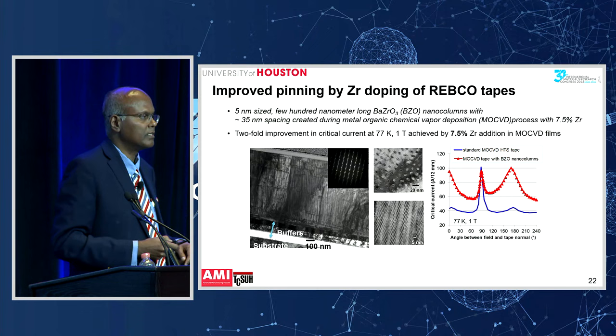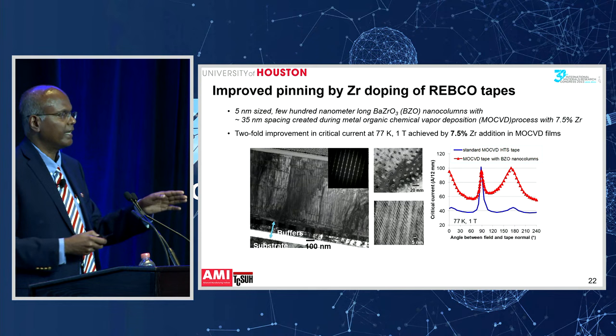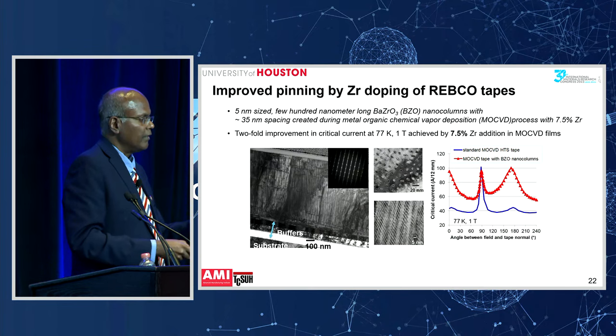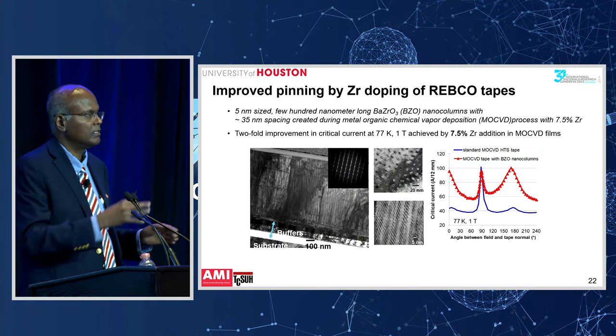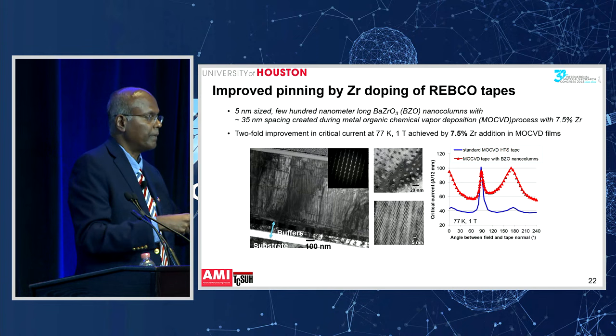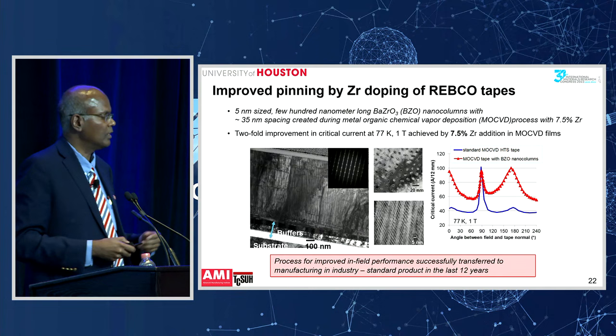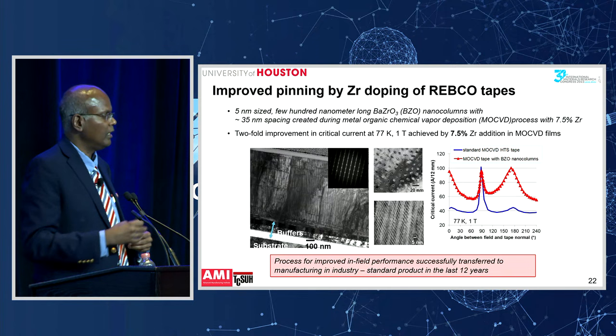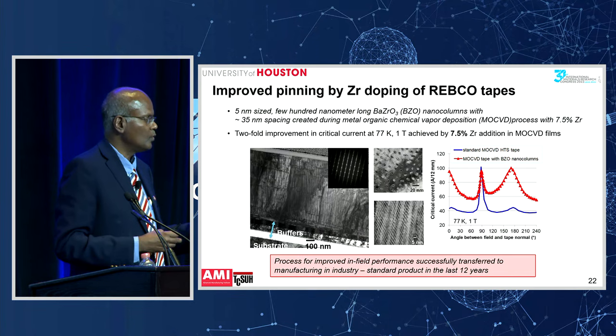So the blue is what I showed you before. When you apply a magnetic field, the current carrying capacity drops off when you align the magnetic field away from the parallel direction. And the red is the film with the nanorods, and you can see a significant boost in the performance, especially when the magnetic field is aligned perpendicular or parallel to the nanorods. This technology was developed more than 10 years ago, and it was actually translated to the industry. A lot of the research that we do, we always make sure it gets transferred to manufacturing, and it's been used as a standard product for quite some time.